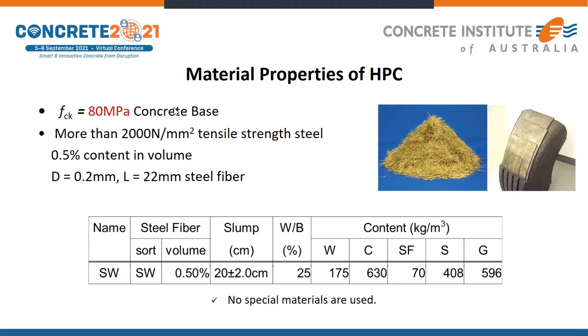So these are the material properties of the high performance concrete. Compressive strength is about 80 MPa, which is not so high. We use 2000 Newton per square millimeter tensile, high strength steel fiber, 0.5% content in volume. This steel comes from the wire of tires. So it is also not a special material, and we can procure it anywhere in the world.